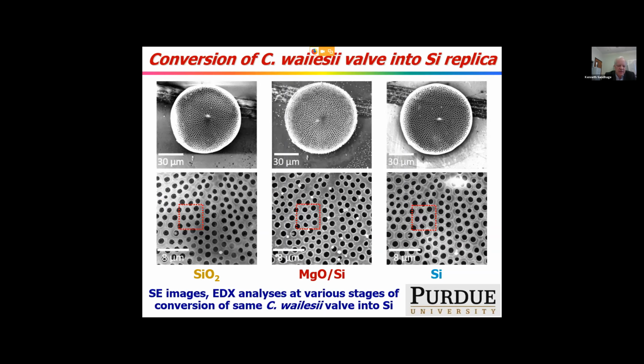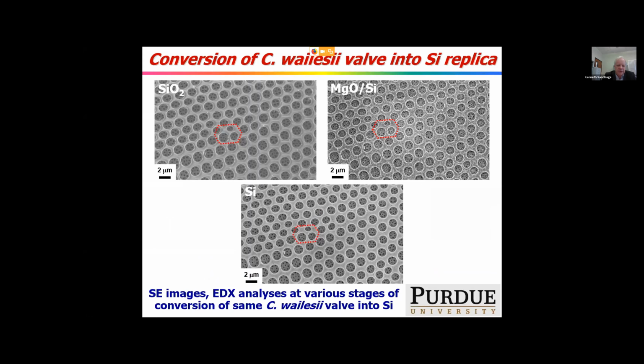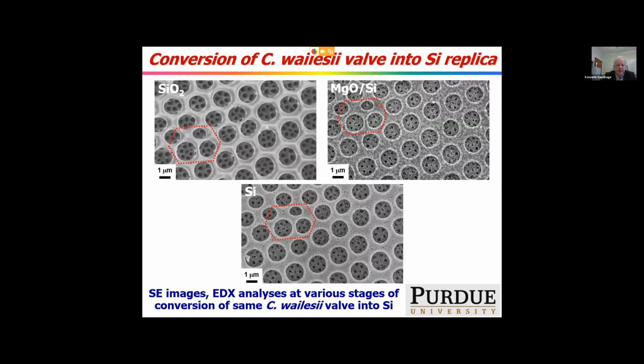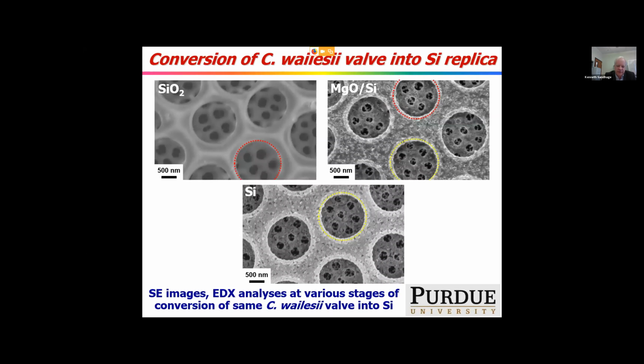You can zoom in. You can see the same 7 large pores are there, pretty preserved at each stage. If you zoom even further, you can see 3 larger pores with smaller pores beneath it, preserved at each stage. If you zoom in even further, you can see even finer, the higher resolution of those pores below. And if you zoom in even further, the red circles are the same big pore, the yellow circles are the same.